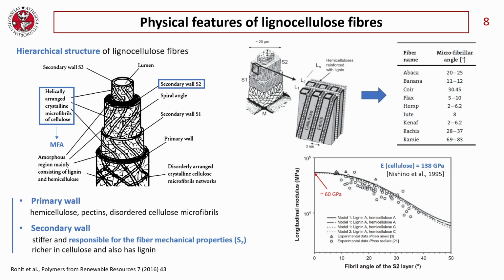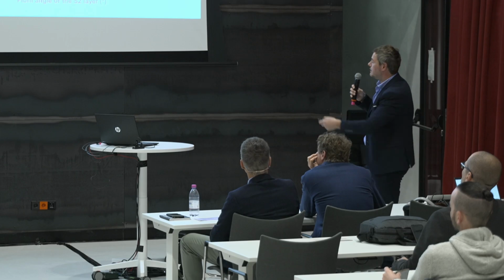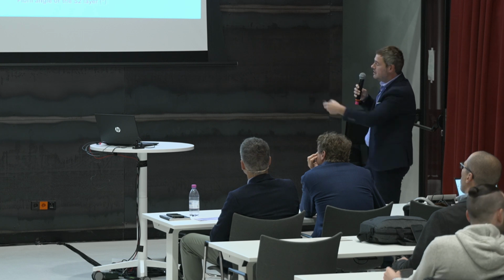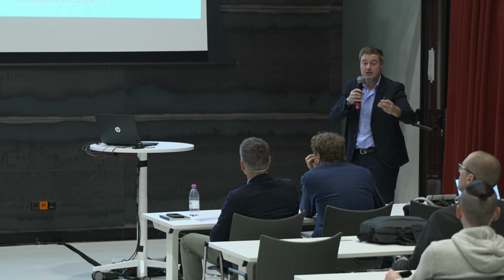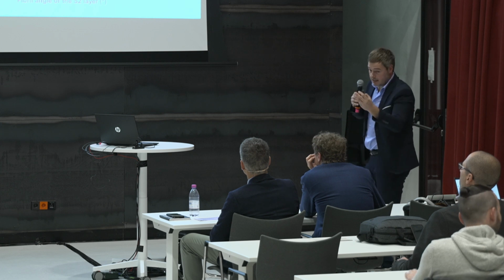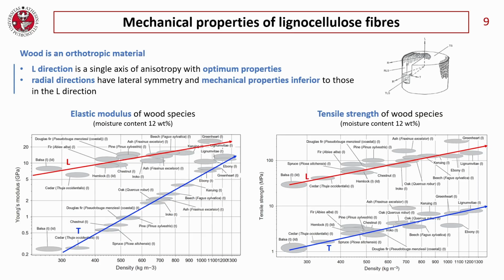The result is that, if we consider lignocellulosic material, we have elastic moduli that could be 20, 30, 40 gigapascal, theoretically. So wood and lignocellulosic fibers are orthotropic, anisotropic materials in which the longitudinal properties are different with respect to the transversal ones. Here you can see the difference between the longitudinal and the transversal elastic modulus of different woods.